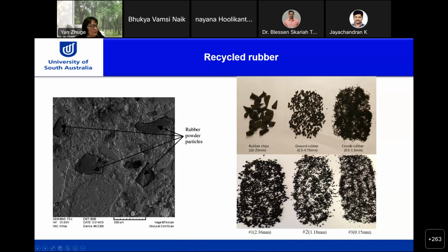I also have the ground rubber. That is the one I talked about before. It's around 0.5 to 4.75 millimeters. These are the major crumb rubber we used, or even a smaller size of crumb rubber, 0.5 to 1.5 mm. We did use both of them, but in the end, we found out a bit smaller size is better.